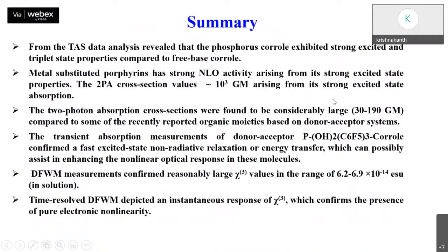This is the summary. There are two corrole systems. Corrole and porphyrin have a strong two-photon absorption cross section of 10 to the power of 3 GM, arising mainly from the strong excited state absorption. From the DFWM measurements, you can have large Chi3 values of 6.2 and 6.9 times 10 to the power minus 14 ESU in solution. All the measurements are performed in solution. Time-resolved DFWM confirms the fast response is mainly arising from its pure electronic contribution.